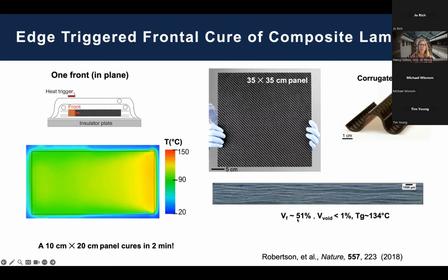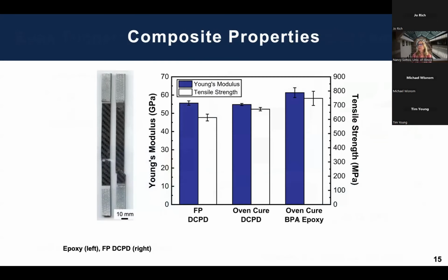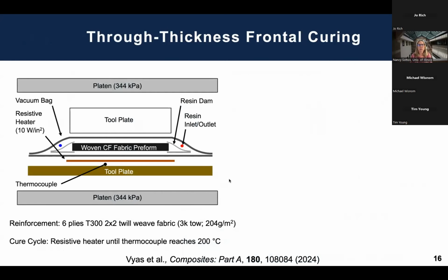It's a nice material. These are all woven that we've looked at. 51% volume fraction in these early ones, low void content, and a pretty good Tg, 134°C, a little bit below that of the neat resin system. That's due to these early processing methods. The properties of the system are pretty good. This is the frontally cured composite compared to an oven cure of the same material, compared to an oven cure, autoclave cure of a similar epoxy, our comparison aerospace grade epoxy. It's a little bit under the mark, but pretty good. And there's things that we've been working on along the way about increasing glass transition temperature. The fibers are all sized for epoxide, so we've got lots of challenges on fiber matrix interface that we've been working on. But overall, a nice result.